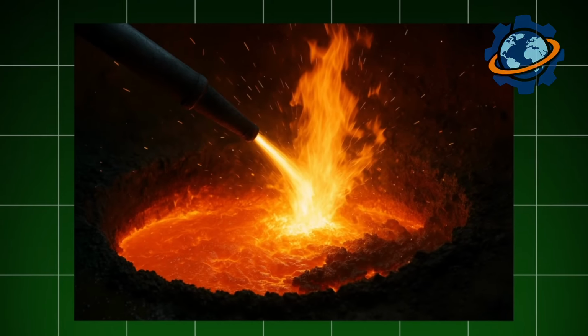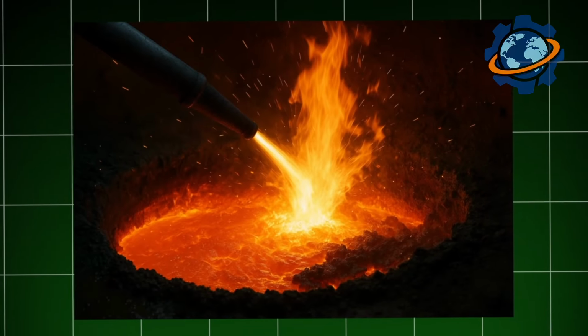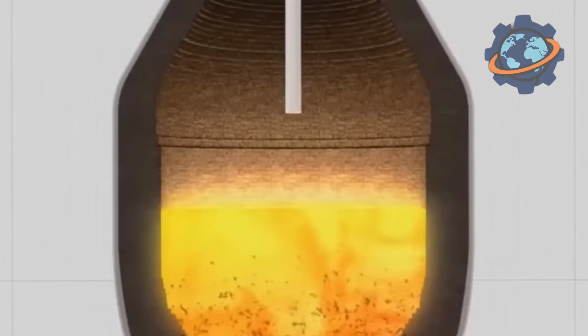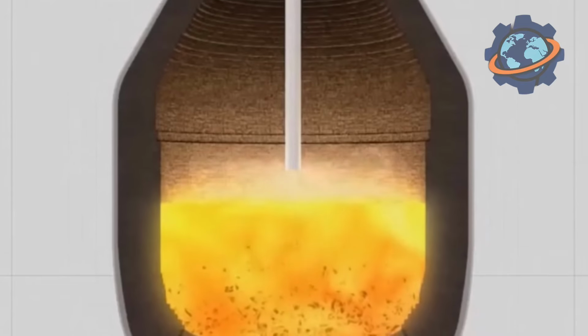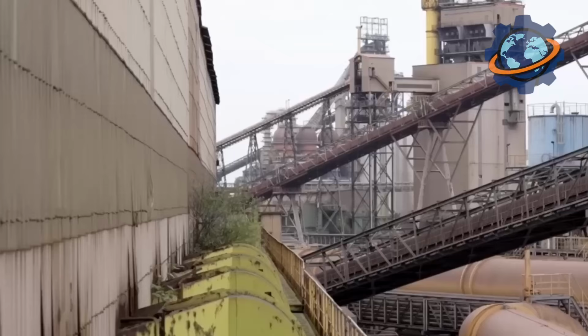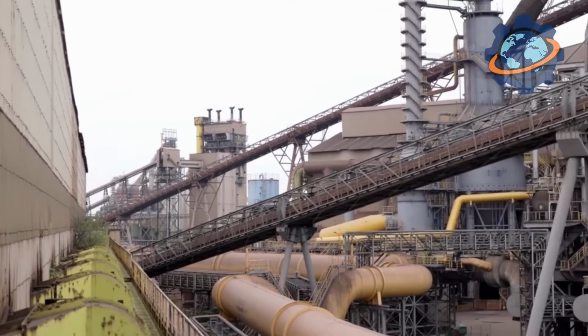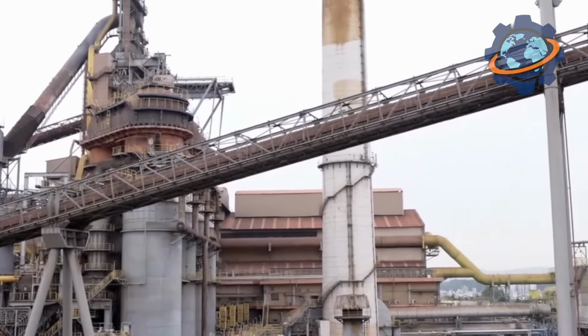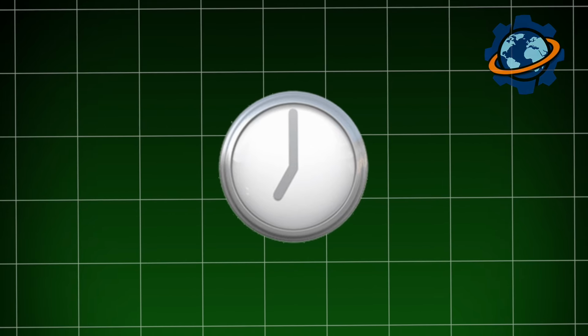Chemical reaction begins instantly. Zinc reacts with iron on the steel surface, forming a layer of intermetallic compounds, a solid alloy of zinc and iron. This layer bonds permanently to the steel. On top, a layer of pure liquid zinc. The beam is held in the bath for 1 to 2 minutes.